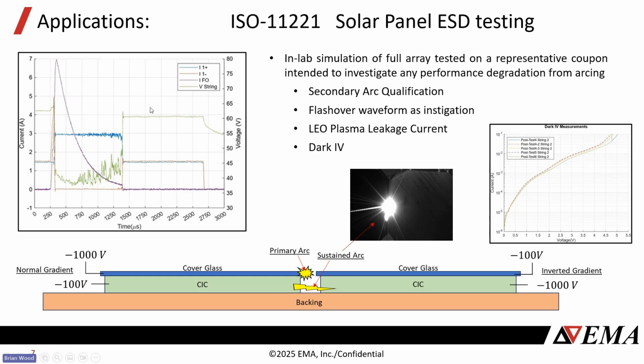And so that plot on the top left here is basically just one of the direct waveforms of one of those interactions. And so that purple line, IFO, stands for the flashover, which is essentially the waveform of just that primary arc. And so we can dictate the strength of that primary arc to help it be more representative of an entire array. And as we run this test, we'll get a primary arc, and then we're also monitoring the current that's going through those strings. And essentially, you're able to determine if there is any amount of current that's going across that gap that persists past what the primary arc is providing. And so that primary arc is essentially providing the plasma to connect those two and form that bridge.